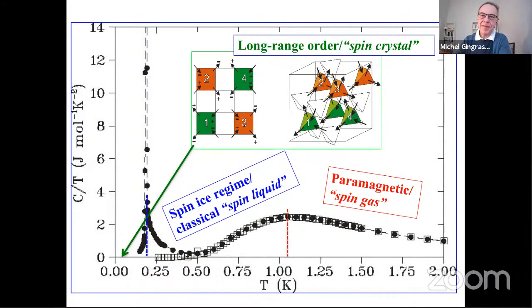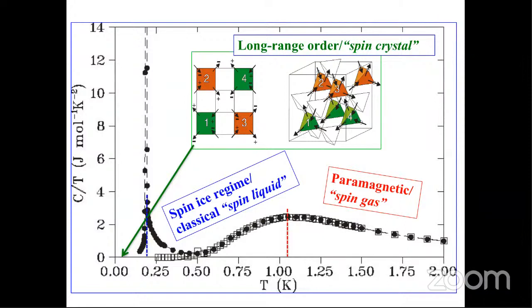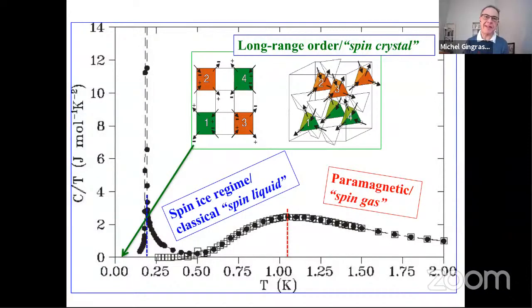15 minutes, okay. So the story of spin ice from an equilibrium point of view should be understood as the following. This is clear, and everybody agrees on that. For the model that I explained, there are three regimes. There's a paramagnet, which is trivial. There's an intermediate low temperature state, which is a strongly correlated state of matter. It's classical. It's very constrained. The dynamics should be extremely slow. And if equilibrium could be maintained, there should be a transition to long range order below a temperature of about 100 millikelvin. This is agreed upon by all theorists in the field.